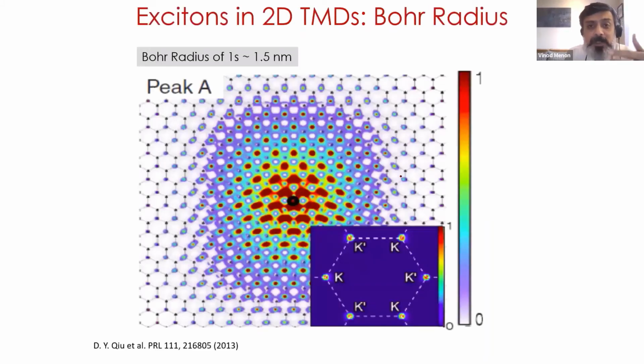If you think about what happens in the case of these 2D transition metal dichalcogenides, the wave function of the excitons is not actually sitting at one atomic site. It's actually distributed over about 15 atomic sites in radius. So the typical radius is about 1.5 to 2 nanometers for the 1s exciton. And so they are highly delocalized.